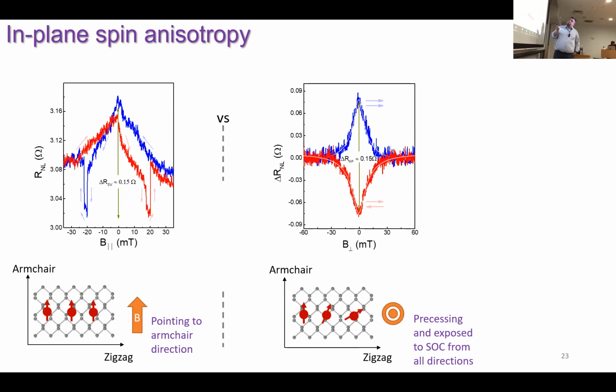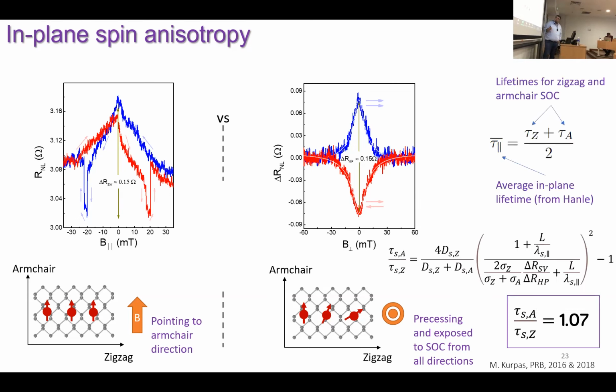For that, you can just compare the spin signals generated in the spin valve and the spin Hanle precession, because in the spin valve, you're injecting spins and they're just moving without any rotation. So they are just being exposed to one single armchair direction. But in the case of the Hanle, you're applying the field and then spins are propagating, rotating within the plane. So they are being exposed to all the directions. By doing some simple simulations, you can extract the spin anisotropy within the plane. So that's what we got. The spin anisotropy within the plane also depends on the gate voltage, but the highest value is around 1.07. And this is also agreeing perfectly with the theoretical predictions done for this material.